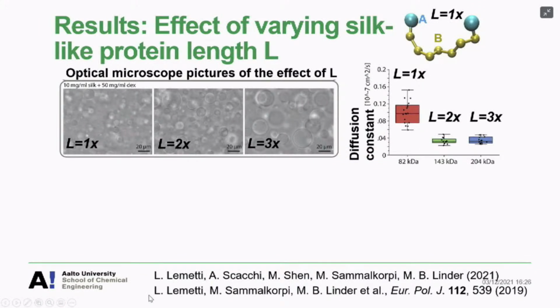Then what can we do with this model? Experimental data on varying the silk-like protein length. In practice, what is being done in experiments is there is one of these silk proteins, but it's connected to another one, so that the end unit beads are also repeated in the middle, by the way that it's constructed into repeating length units. And experimentally, we know that the condensate structure is quite dependent on how long the silk-like protein is. So is it 1 repeat, 2, or 3? It's also affecting quite a bit the dynamics, so the diffusion coefficient of the proteins, and also how those droplets are coalescing. That data I'm not showing here, but the viscosity of the solution is also dependent on the chain length.